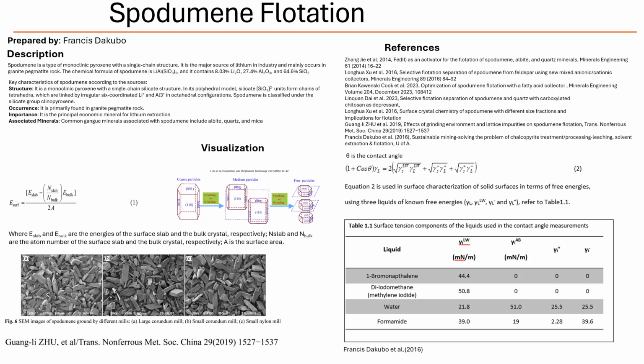And the chemical toolkit is sophisticated. Collectors like NaOL to make spodumene float, activators potentially boosting them, and depressants like maybe even chitosan derivatives to keep the unwanted stuff down. Don't forget, particle size being key, finding that optimal range to expose the right crystal faces like the preferred cleavage plane. And computational modeling is really helping us understand why these things work at the atomic level. And finally, putting it all together in the plant involves careful control over conditioning pH, dosage, time, mixing energy, always balancing that trade-off between recovery and grade.